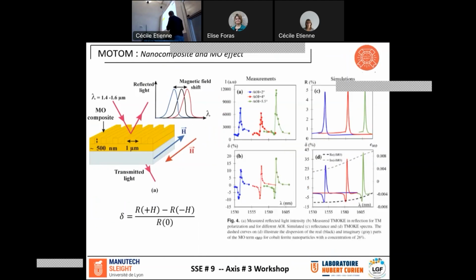You have a one-dimensional microstructured surface on a substrate. It behaves as a guided mode resonant device, so you have a large reflection. And when you apply a magnetic field in one direction or the other direction, you can shift the resonance. If you measure the shift of the resonance, we have obtained more than 20% shifting of the resonance with the magnetic field. Oh, this is what we have done before. This is not exactly what we want to do in that project.